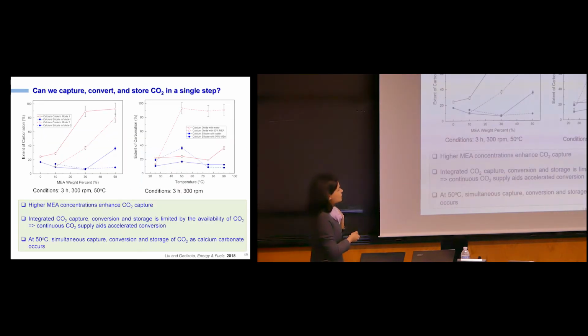So we just started doing this with calcium oxides and calcium silicates, and it turns out that with calcium oxides we can see close to 100% conversion at temperatures at about 50 degrees centigrade with 38% of the amine with mode 1. This is the mode where we have gas, liquid, and solid. With mode 2, where we just have liquid-solid contacting, we run out of CO2, which is one of the reasons why conversions are slightly low. Also with silicates, we see about 30% conversion.